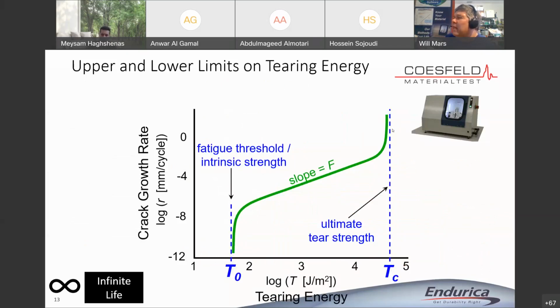Talking about infinite life. This is a picture of rubber's fatigue crack growth rate curve, right? On the high end, you have the strength of the material, T_c. On the low end, you have the fatigue limit, T_0. And in between, you've got this green curve that controls, for a given fracture mechanical energy release rate, what is the rate of growth of the crack. Now if you're in the infinite life approach, the only thing you need to know is this lower bound, right? I don't need to know anything about the rest of the curve. I just need to know that lower bound, and I need to make sure I'm below it.